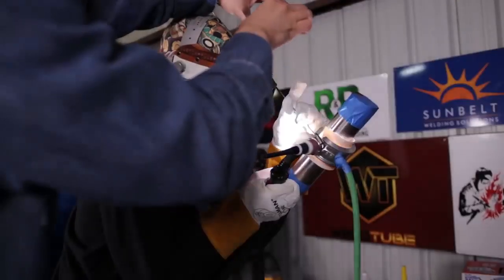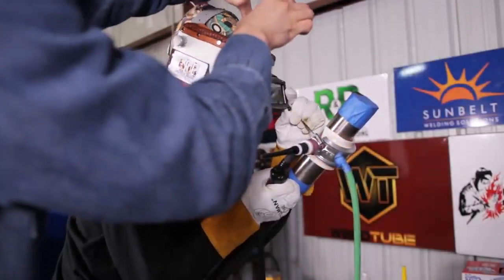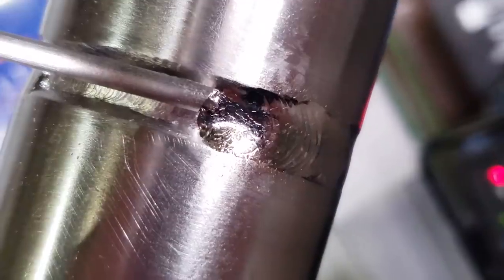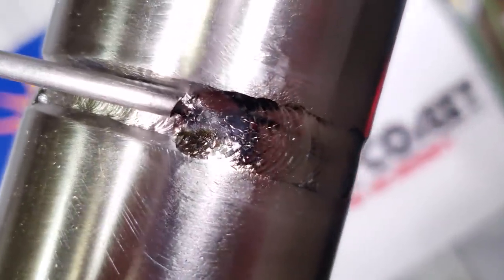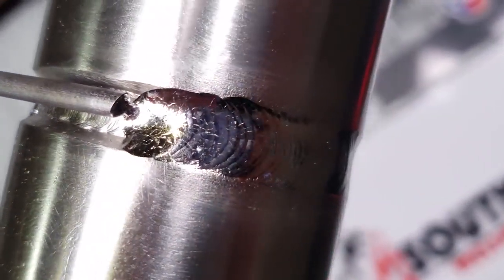But if you have light straw color for heat tint oxidization on the heat affected zone, if you have any oxidization in the heat affected zone, then it means that every individual ripple that you create, you protect away from the atmosphere for a couple seconds longer, another 2 seconds. And it's just an accumulation of heat over a distance.